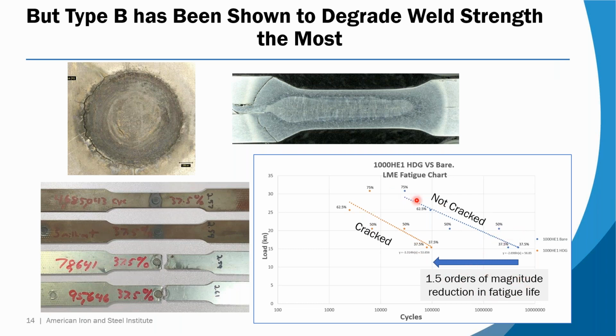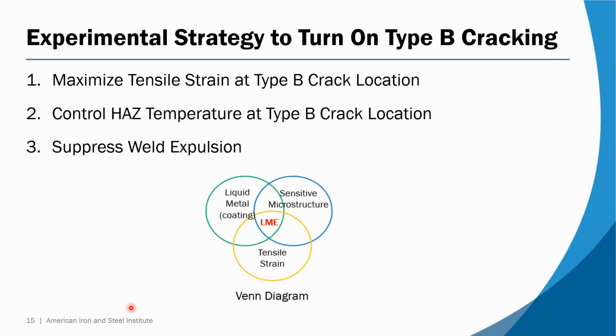Okay, the blue line here is samples like these, which have the zinc removed, so we know there's no weld cracking. The zinc was stripped off, then welded, and we got this fatigue line. When we left the zinc there and did basically the same welds, we had cracks, and there was a big drop in fatigue life from 5 million down to less than 100,000. So type B is the one we would really like to turn off.